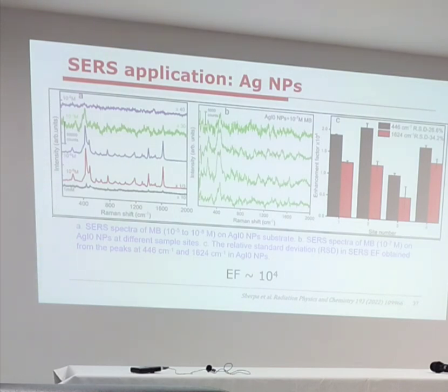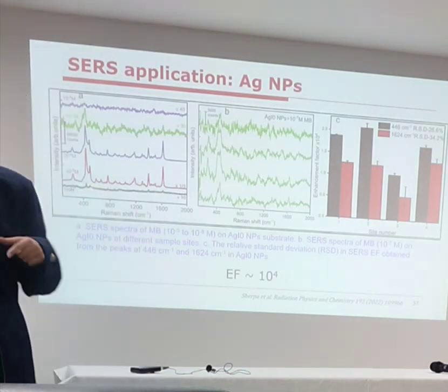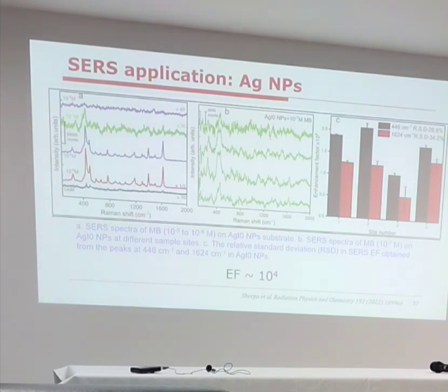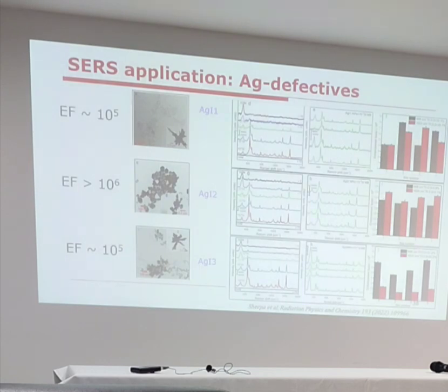Good enough, but now I irradiated that synthesis process, and because of that I ended up getting those dendrite assemblies, defective particles, and larger particles inside the system. Owing to that, I see these self-assemblies of particles up here. Because of these self-assemblies, I begin to see that the enhancement factor is also increasing, one-fold, two-fold, and so on. So defects, as I said, are rather good compared to something more precisely ideal in terms of shape.